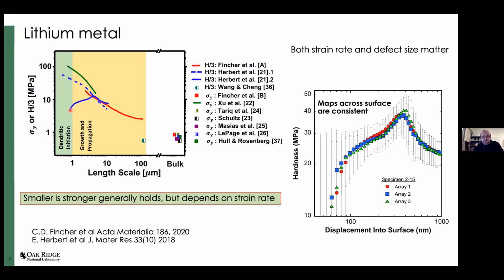However, there is this curve here obtained at relatively slow strain rate by nano-indentation by Eric Herbert. And you can see that even at the small length scale, you have lower strengths of lithium compared to the high strain rate experiments. So this has been checked over many different samples, and you can see it here as well. As the length scale of your defect increases, your strength of lithium, hardness, or ability to support some pressure goes up as well, and then it goes down.